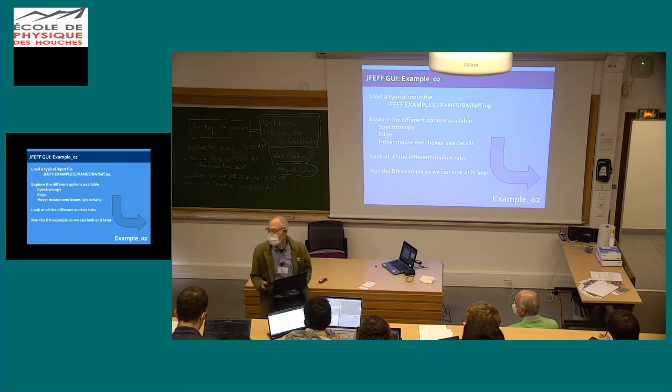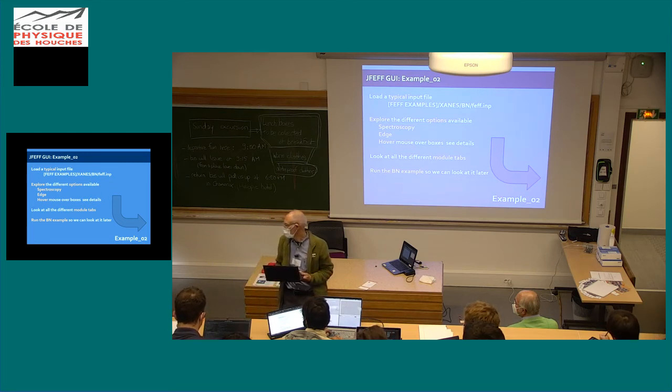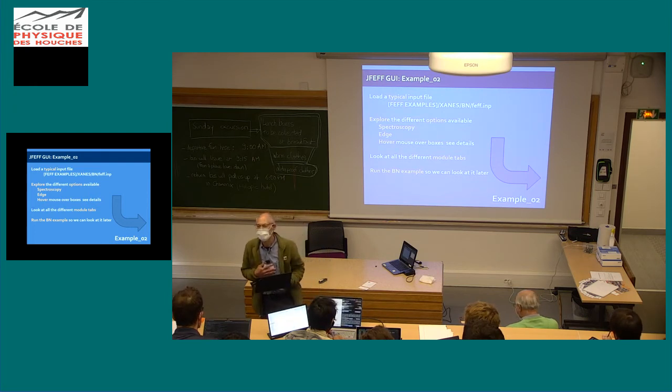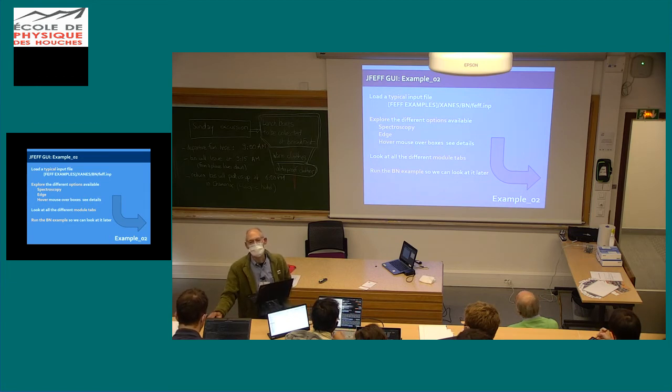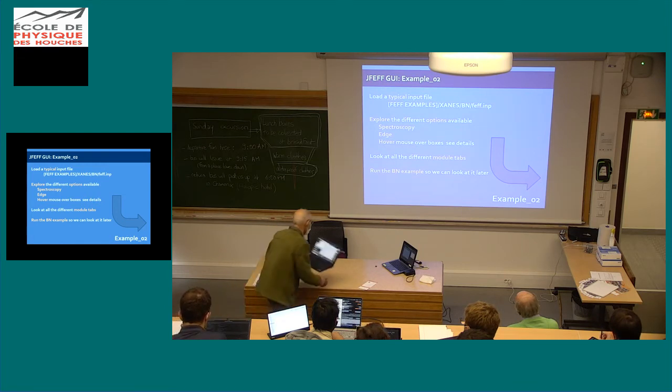For L-shell metals, as Hubert knows, you turn the core hole off, right? Yeah, nobody knows why. Or at least I don't really know why. It appears to be very strongly screened, so you get better results without a core hole. Actually, you really need to do a Bethe-Salpeter or a better calculation on that. Okay.